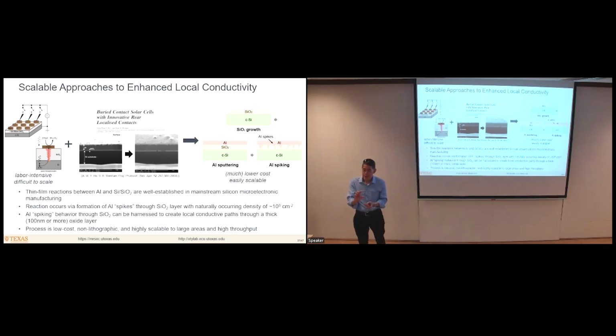If you have aluminum, say on top of silicon, it was known from the early days of making ohmic contacts that if you annealed it to form the contact, the aluminum would form localized spikes that penetrated into the silicon. This was bad for devices because it would short out the underlying device structure, but it was good for applications like this, where you wanted ohmic contact through an SiO2 layer to a silicon layer. You anneal this structure and form just these localized contacts through the oxide, and you get a good enough ohmic contact while retaining most of the silicon-silicon dioxide interface, which gives you good passivation. So it prevents high surface recombination velocity. This is the cartoon version of that process.